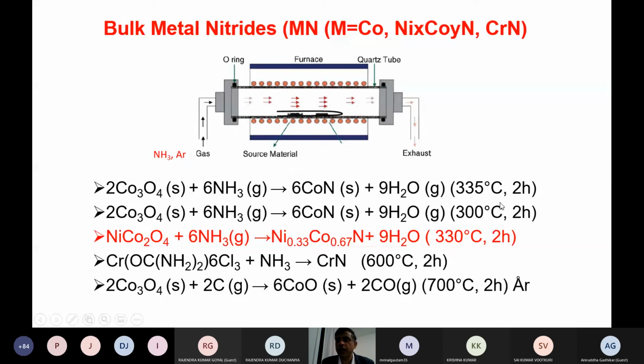Remember, don't use too high a temperature. I think 300 to 335 is the best temperature for cobalt nitride. Suppose you try a high temperature, you will get Co2N, a metallic nitride, and cobalt mixed phases, so it's not really good for the applications. Maybe some other application may be okay, but for energy applications, this may not be interesting. And suppose you want to do some doping, you try to prepare NiCo2O4, pass the ammonia gas, and we can get the respective nickel-doped compounds.